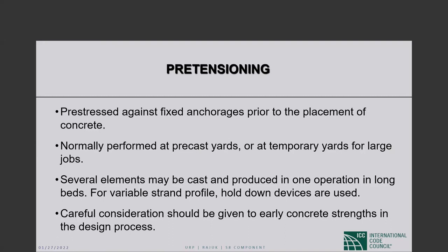So one issue is that we must be very careful when the stress is released. That's very important for pre-stressed concrete structures. The photograph I showed you of the precast yard. Now, after steam curing, the stress is released, pre-tensioning is released after say 2 days, sometimes we forget that the concrete is very green at the time, right? When we talk about f'c, the design concrete strength, which is typically in the as-built plans, we can say, well, that's a 28-day strength based on ASTM testing of 3 cylinders. But the strength at the time is not what you have in a green concrete in 2 or 3 days.